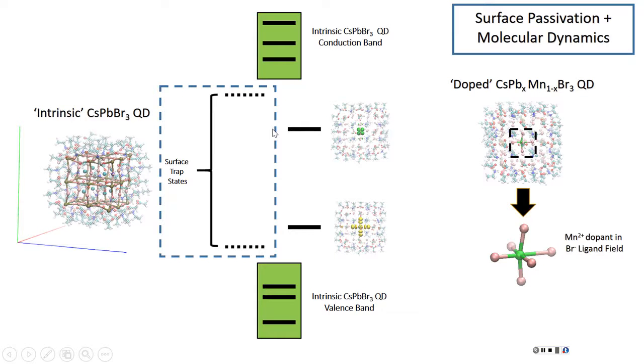So, next thing we add to our figure is we did our electronic structure. Now we're going to look at the role that ligands can play in introducing states within the band gap, or surface trap states, which is usually reported, which is one thing that's been called out in the literature. And the expectation is that for the intrinsic dot, you can have ligands either oscillate with the bonds, and then you can see changes in oscillator strengths just due to bond vibrations, or they could even pop off during molecular dynamics. So if they pop off, or if there are any changes in oscillator strengths, you should be able to see that along your trajectory.